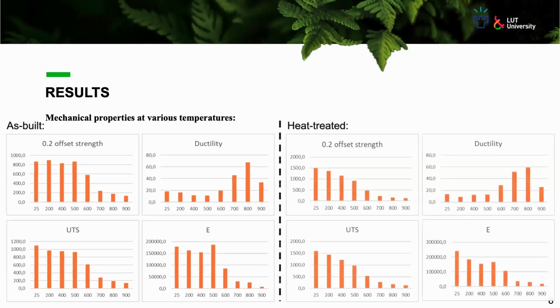And if you compare the behavior of the material at different temperatures in this as-built version compared to the heat-treated version, the heat-treated version had a more normalized behavior. We believe that's because the heat-treated version's strength and ductility heavily rely on the presence of beta particles, and its strength starts to decrease because by increasing the temperature, the solubility of these particles increases and they vanish from the background structure. Combined with the tempering effect of the martensitic phase, this causes a smooth decline in the strength values and, on the other hand, an increase in ductility.